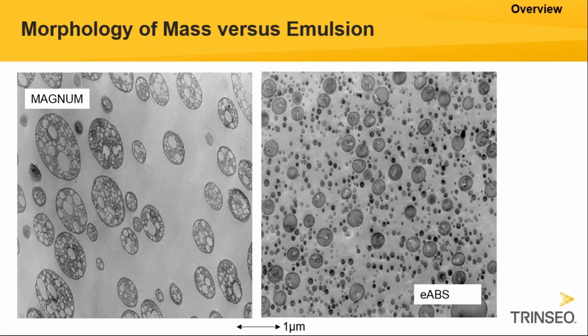Now, in this slide, I want to highlight the morphology difference between mass and emulsion ABS. And you see here two electron microscopy pictures. Let's first focus on the picture on the left side, which shows the Magnum ABS. Now the light gray background, that's the SAN polymer matrix. And the dark gray spherical particles, they are the rubber particles. This darker color is the result of a sample pre-treatment process, which is called staining. And this staining process acts specifically on the carbon-carbon double covalent bonds which are present in the rubber. And then in an electron microscopy picture, they are highlighted as darker gray zones.